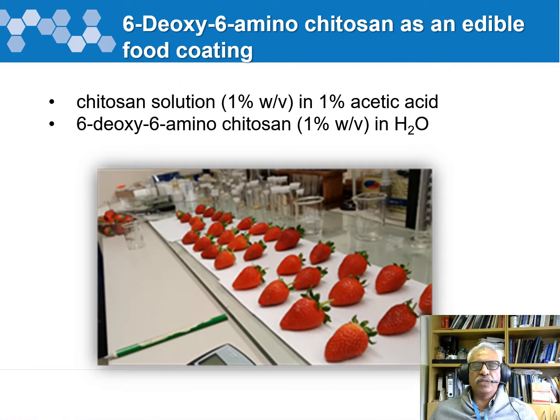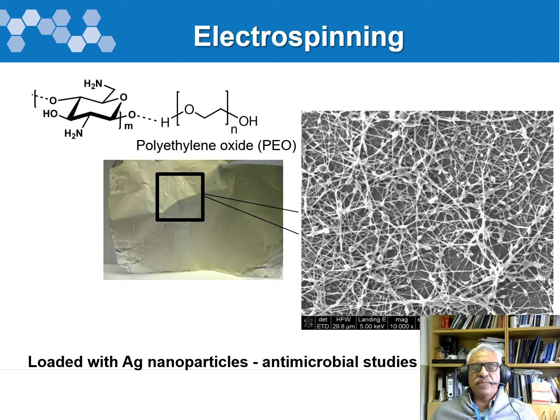And we've done some coatings on strawberries. It does increase the shelf life by at least 3-4 days by just spraying a coating of 6-deoxy amino chitosan on there. You obviously can't spray with chitosan because it's extremely viscous, and your maximum concentration you can get in acetic acid is 1%. We've also tried electrospinning of this material, and then loaded with silver and showed that it also forms antimicrobial fibers.